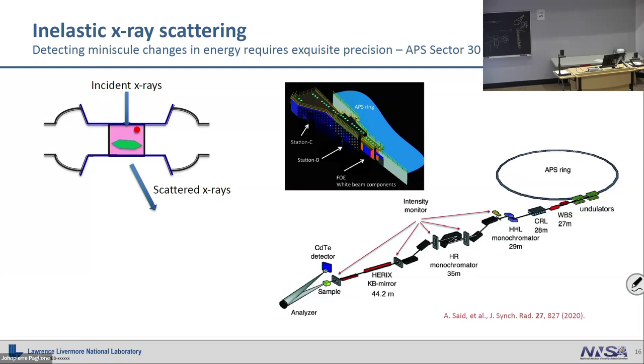The problem is that doing that at the beam line where you do inelastic scattering doesn't work very well. So most of the time you have to build a DAC, go to some other beam line, and figure out how it's oriented well enough that you can bring it to this particular beam line. This is the HERIX. Again, it's at the APS, sector 30, I think. And this is a beamline that's basically specialized just to do inelastic X-ray scattering. So same kinds of information you're going to get from inelastic neutron scattering, just in the X-ray regime.